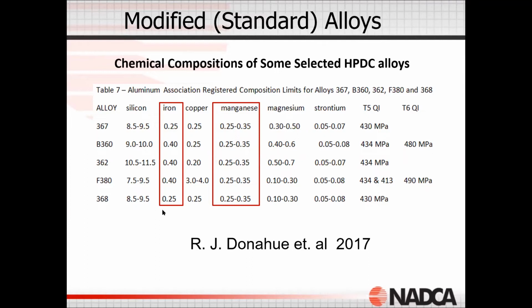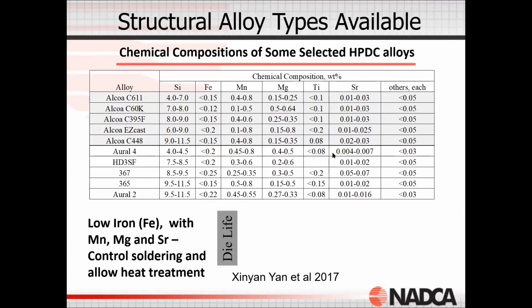What I've outlined here are the iron and manganese levels, because in these alloys, we're maintaining silicon levels to give us good fluidity, but then we're dropping the iron level and controlling the manganese to give us castings that are less brittle and higher elongation alloys. So with these alloys, we have the iron and the manganese combining to enhance the die life. We're adding magnesium for strengthening, and strontium is being added at certain levels for silicon modification. So we're modifying the silicon in the aluminum from a needle-like structure to more of a nodular structure.